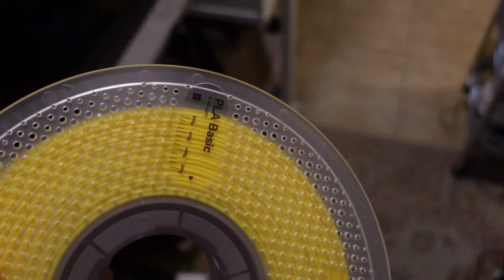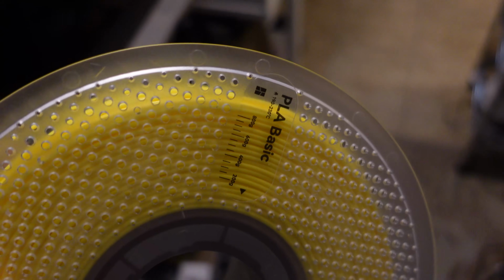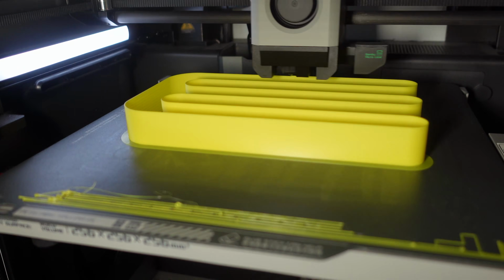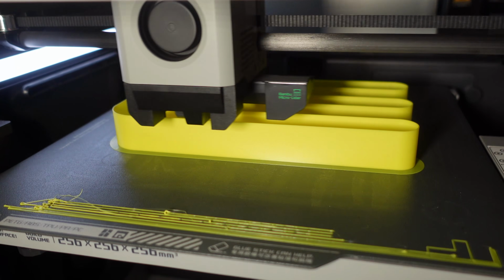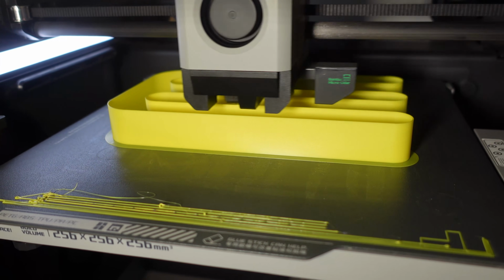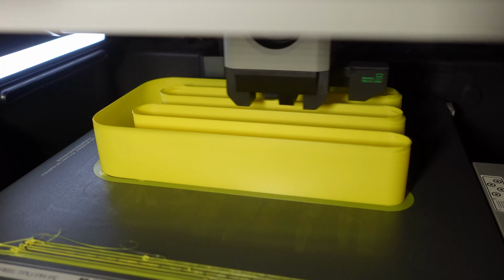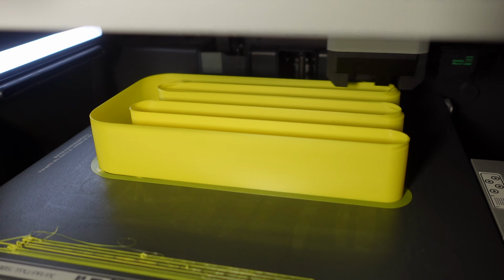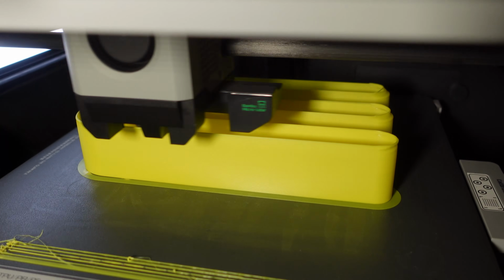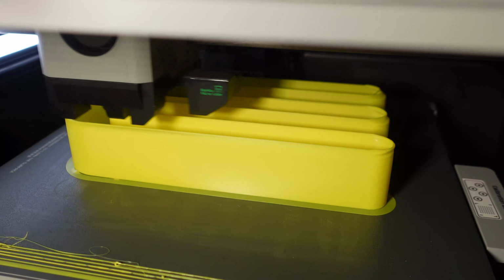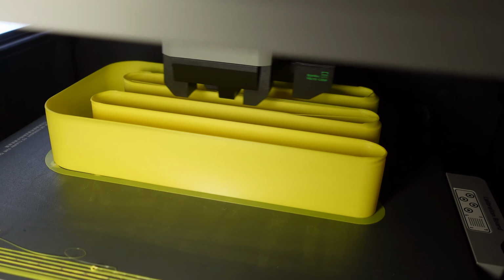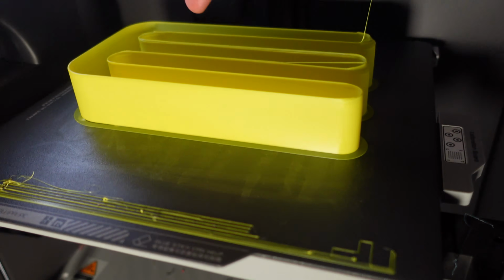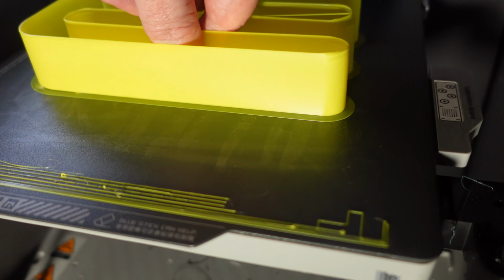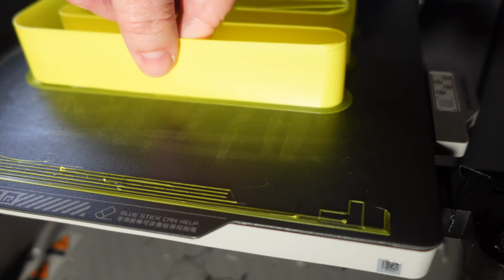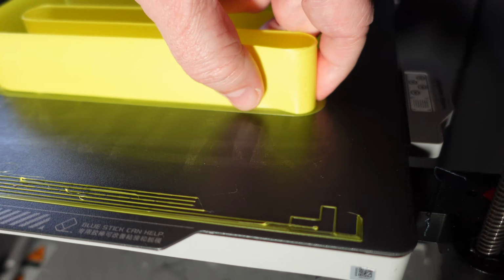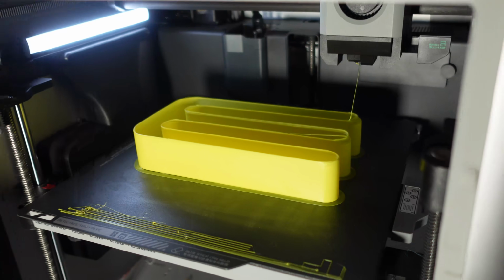PLA Basic, I hope it will be good for the comparison. Printing at 65%. I could hear a few skips of the extruder, but visually the printing looks okay. Printing at 76%. Now I can see some serious under extrusion, so I will stop the printing and I will analyze it. And just to show you the difference in bed adhesion, well, I cannot even remove it. I have to wait until it cools down.